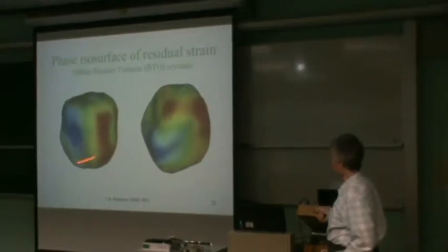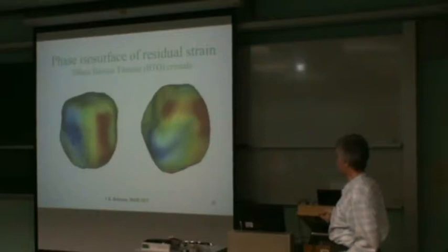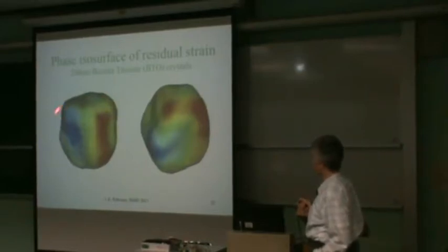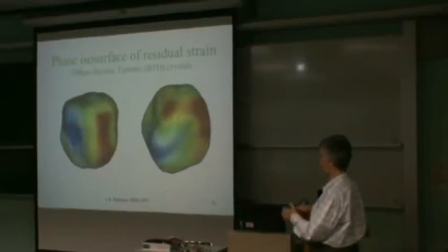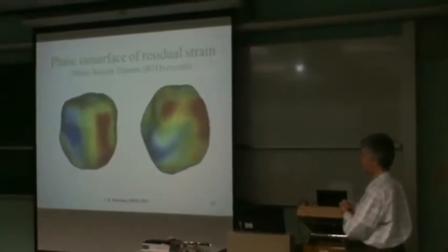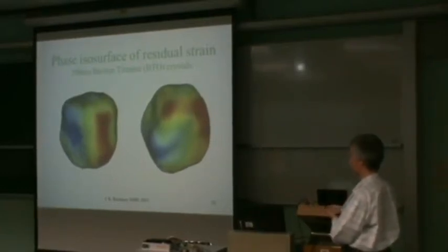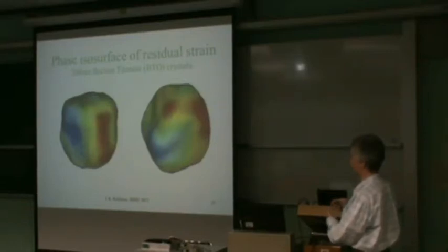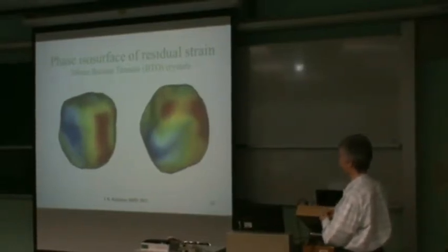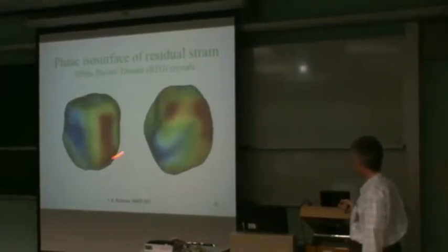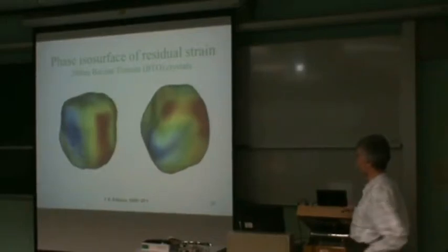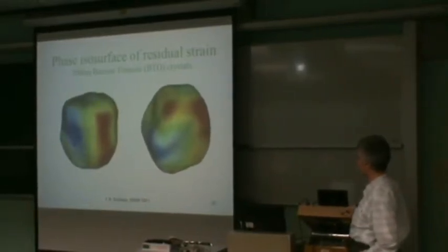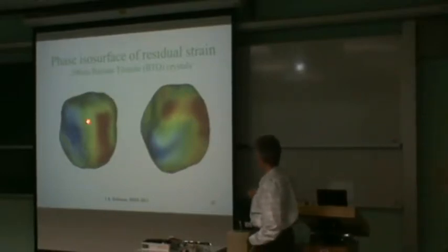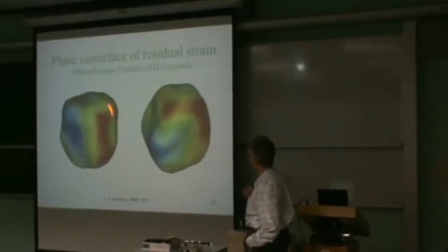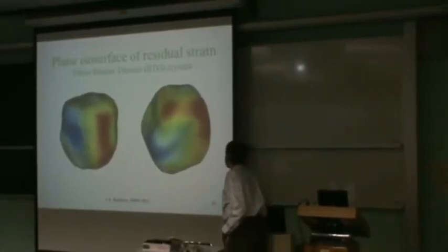Here we're seeing, again, the surface of one of these particles. It's roughly spherical in shape. We're just looking at a single particle, 200 nanometers in diameter, and it's got a strong phase structure present. This is due to the presence of some distorted shell of material, which is reverting to the cubic phase, perhaps, viewed with one of the peaks of the tetragonal phase inside, and so the distortion looks like a strain. And we've got quantitative mapping of that strain all over the skin, all over the bulk of the material, and it shows up most strongly at the surface as this rich pattern of phase, which is shown on a scale where blue is minus pi and red is pi. So we've got a full 2 pi variation of the phase.